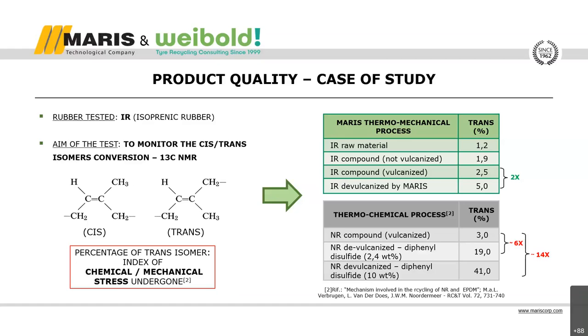The results obtained and the literature evidence show that both vulcanized materials have a certain level of trans isomer. And during the devulcanization process, the percentage of trans isomer increases. But the big difference is that the increase of trans isomer percentage for the MARIS devulcanization process is lower compared to the thermochemical process, which, as a function of the percentage of devulcanizing agent added, the trans isomer percentage increased much more, 6 times or 14 times more. Summarizing, the evidence shows that we are able to limit the degradation of the rubber during our process.